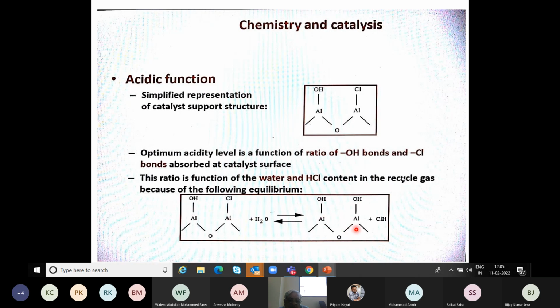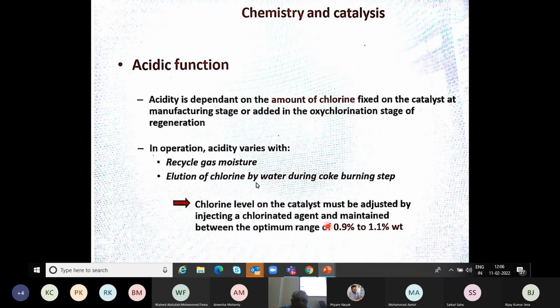In reformers, this chlorine keeps on leaching out as the reaction happens. So we have to continuously add a chemical which brings in chlorine along with it, something like carbon tetrachloride or chloroform and things like that. So a chlorine containing hydrocarbon is added to maintain the acidity of this catalyst. This is just to get deeper into it. As I said, the chlorine level on the catalyst must be adjusted to between 0.9 to 1.1% by weight, and it continuously leaches out.